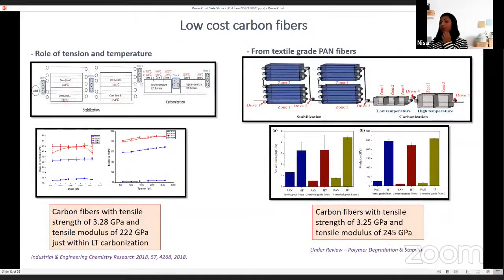We were also interested to make changes in the carbon fiber production line, or try using alternate precursor fibers to come up with cost-effective ways to make carbon fibers. So in one study, we applied a higher tension by using a lower temperature in the furnaces, and we wanted to check the final carbon fiber properties. We found that we come up with automobile grade carbon fibers just in the lower temperature furnace.